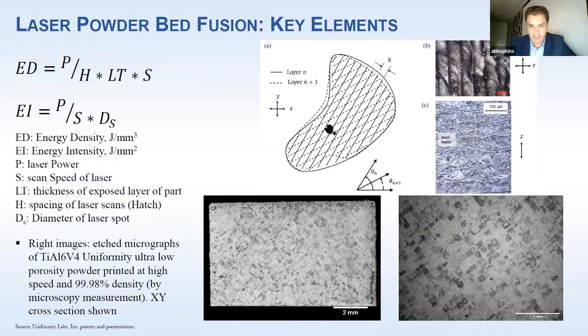Here's a scan pattern that you might see. You have fill, where you scan in the middle. Then you have a contour, just a single scan around the edge. That's to take care of the problems you have when you turn the laser off after scanning these hatches, because turning the laser off introduces defects of various different types. I won't go into the details there, but you need a contour to fix those defects and to smooth out the surface of the part.